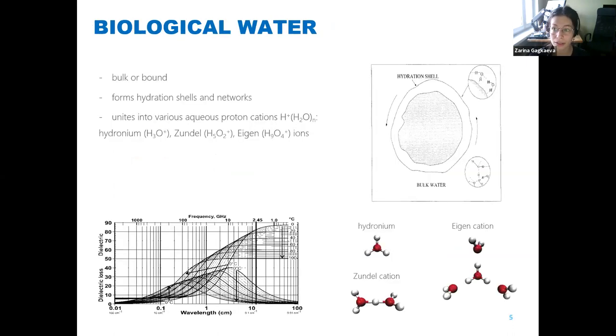In biological materials, water is not the same thing as the water in the glass, so it usually exists in different bound states. Water molecules form hydration shells and hydration networks within the bulk of the biological material. While protonated, water molecules form different clusters and different protonic species, such as hydronium, Zundel cation, or Eigen cation, and these cation elements are regarded to be the major participants of charge transport processes.